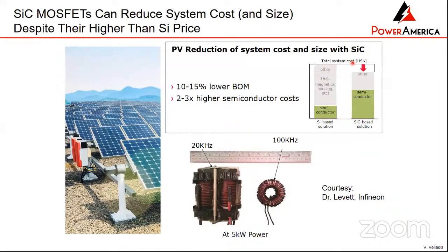If you look at the total cost of a photovoltaic inverter system, you can see that if you use silicon, it's right here. If you use silicon carbide, it's lower. The silicon semiconductor versus the silicon carbide semiconductor have a price difference of 3 times. So the silicon carbide semiconductor is 3 times more expensive than the silicon semiconductor, but the overall system for silicon carbide is lower. And this is because you're able to operate at higher frequencies. This is basically the magnetics for silicon operation, which is limited to lower frequencies, 20 kilohertz. When you get to silicon carbide, where you go to 100 kilohertz, then as you can see, this becomes a lot smaller and a lot lighter and therefore a lot cheaper.